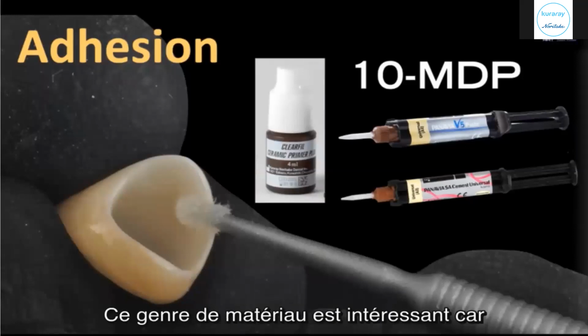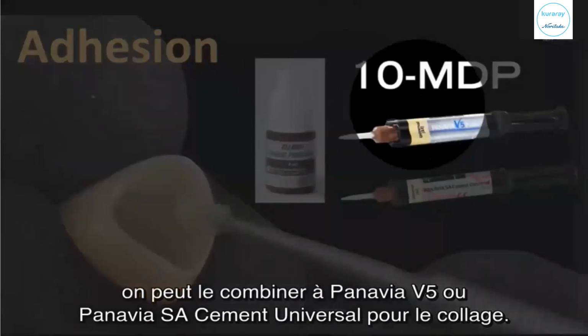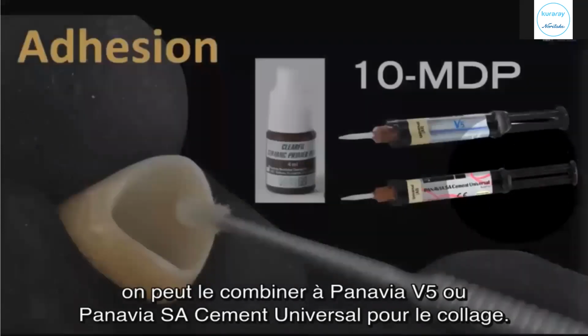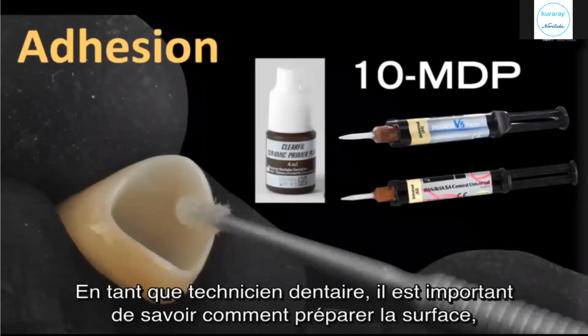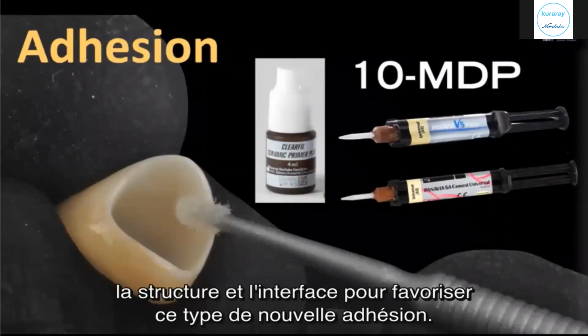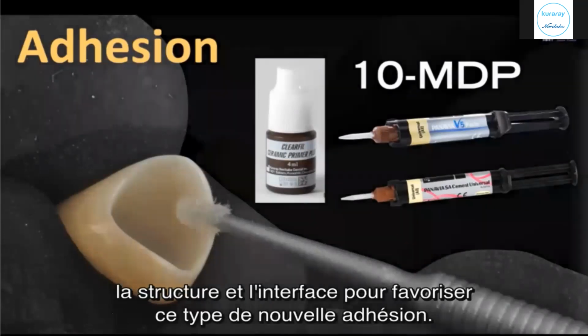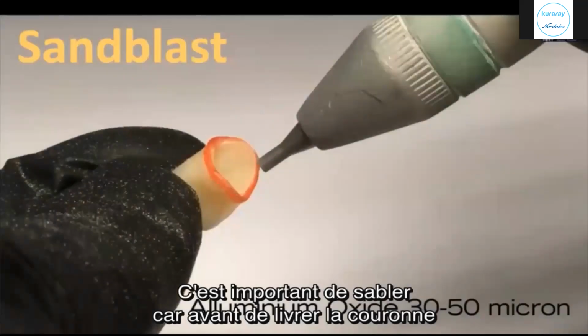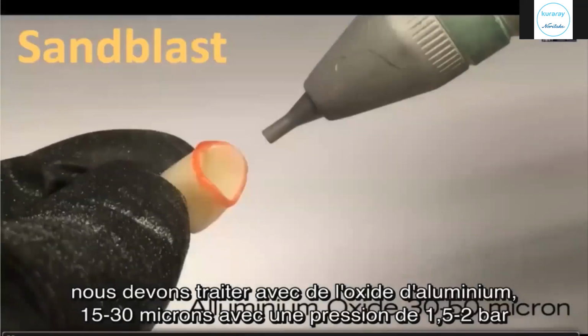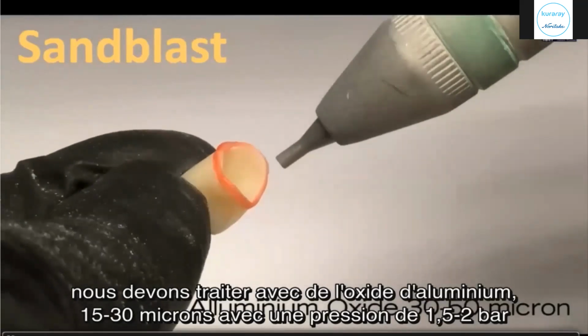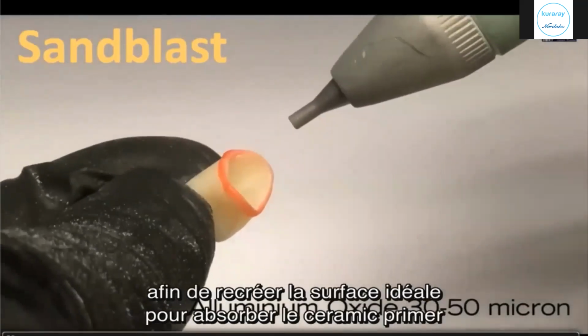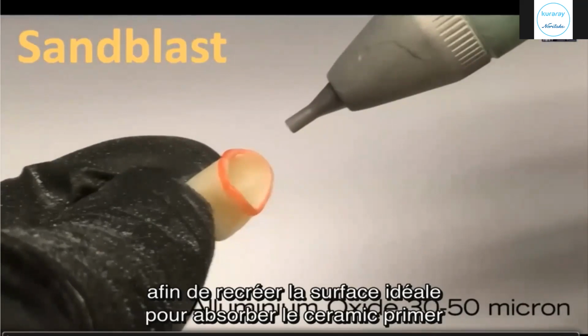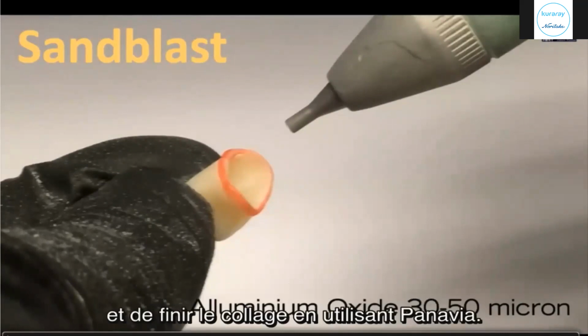This kind of material is interesting because it's possible to combine it with the Panavia V5 or Panavia SA for the cementation. And as a dental technician, it's important to know how to prepare the surface, the structure, the interface to favor this kind of new adhesion. And it's very important to mention the importance of the sandblast, because before delivering our crown, we have to treat it with aluminum oxide 50 micron at 1 to 2 bar in order to recreate the surface ideal to absorb the ceramic primer and to finalize the adhesion cementation using Panavia.